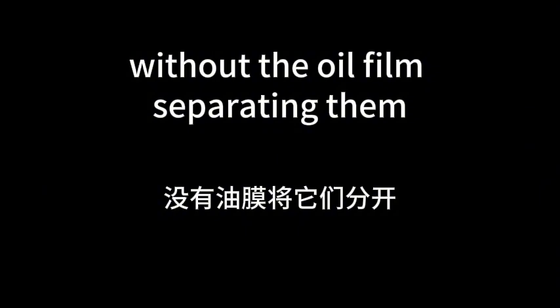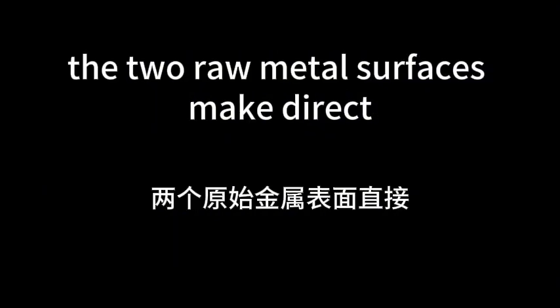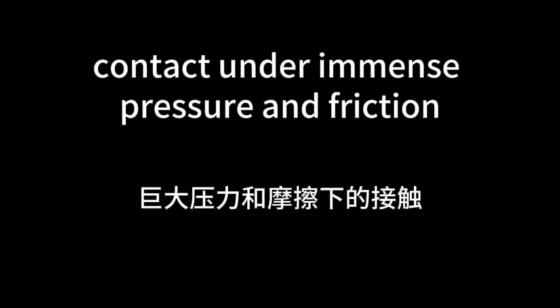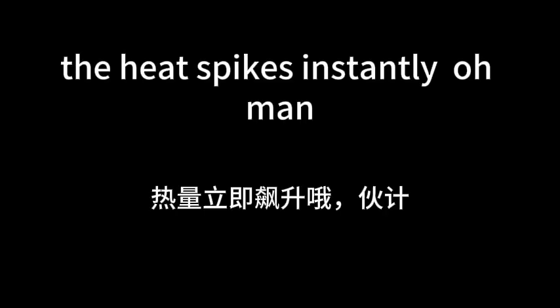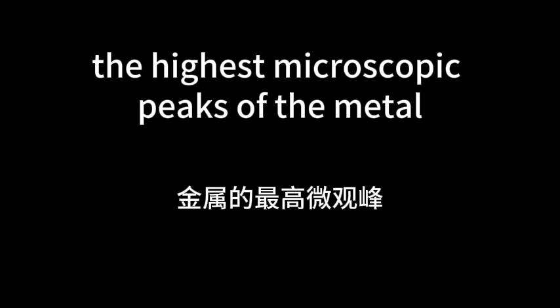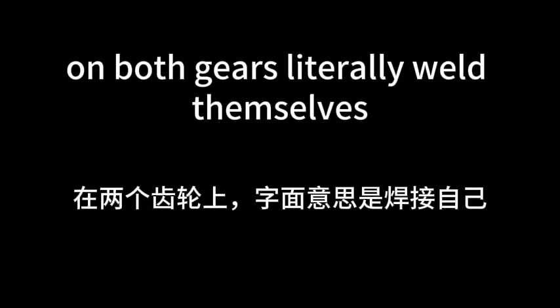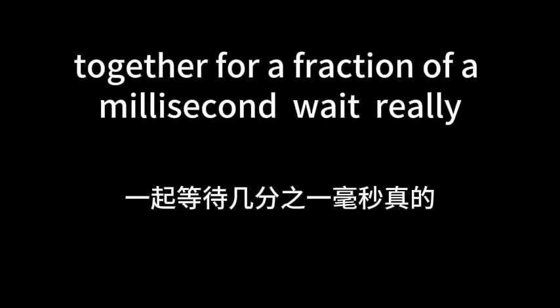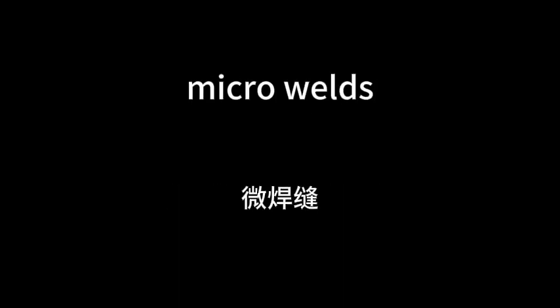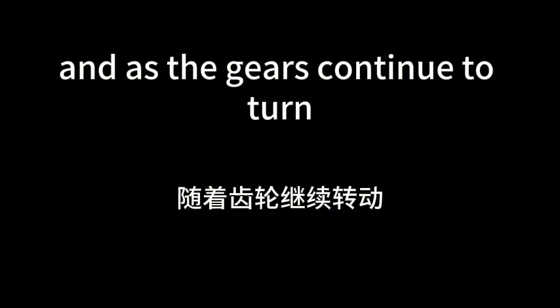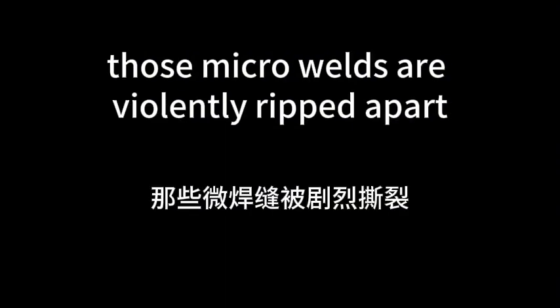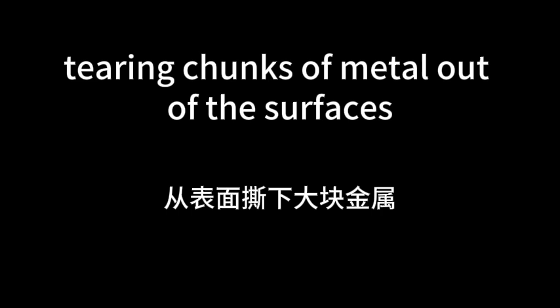Without the oil film separating them, the two raw metal surfaces make direct contact under immense pressure and friction. The heat spikes instantly. Oh, man. The highest microscopic peaks of the metal on both gears literally weld themselves together for a fraction of a millisecond. Wait, really? They weld together? Yes, micro welds. And as the gears continue to turn, those micro welds are violently ripped apart, tearing chunks of metal out of the surfaces.